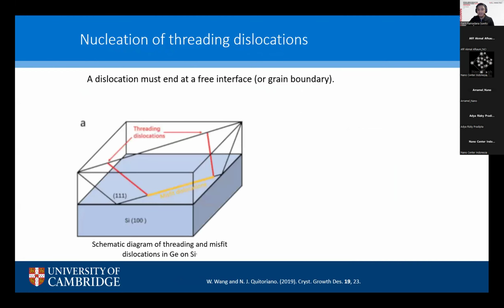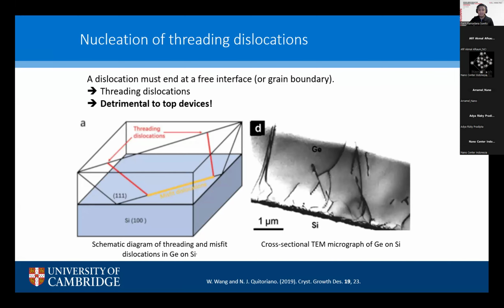Okay, so now we know that a dislocation must end at a free interface or grain boundary. Therefore, the previous misfit dislocations, colored yellow in here, must glide to the surface. This extension of the misfit dislocation is called a threading dislocation, shown in the red colored pictures, and hence it's residing on the surface and is detrimental to top devices. So this is the TEM image of germanium films grown on silicon with a very high density of threading dislocations. And these dislocations can act as scattering centers for the operation of whatever devices you try to grow on top of this layer.